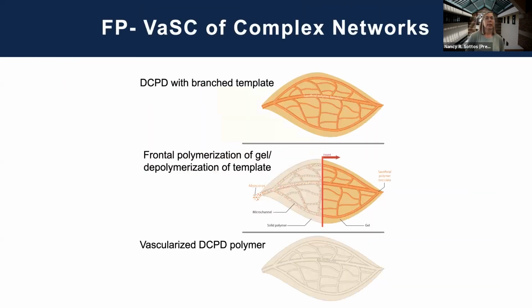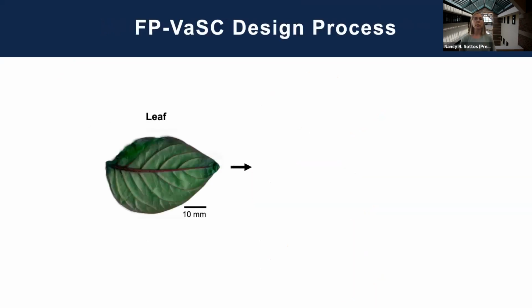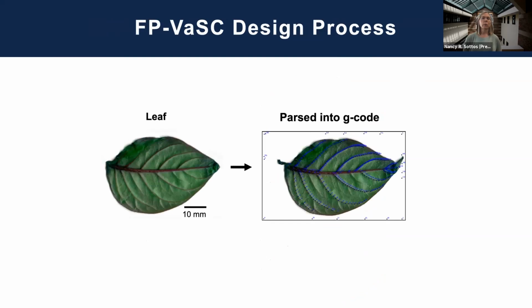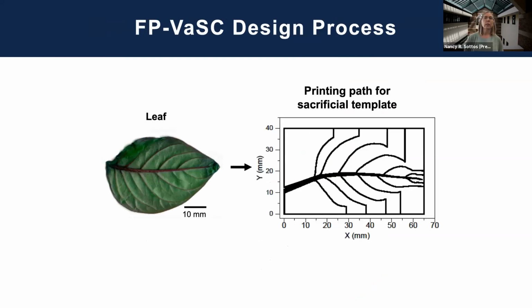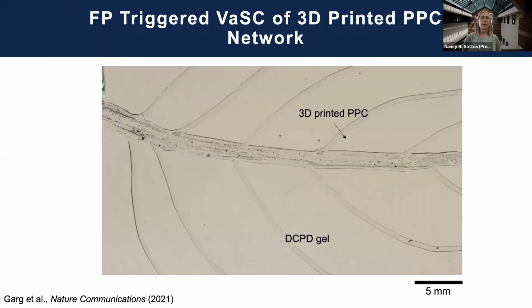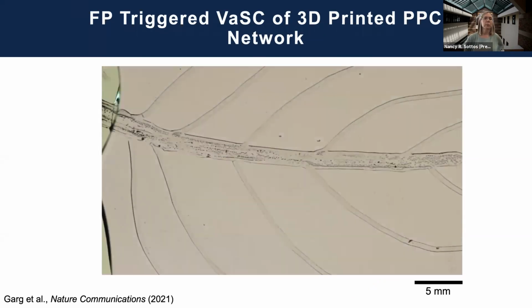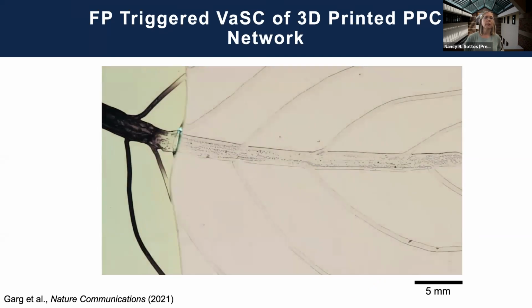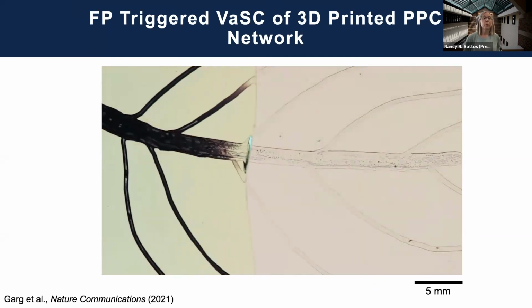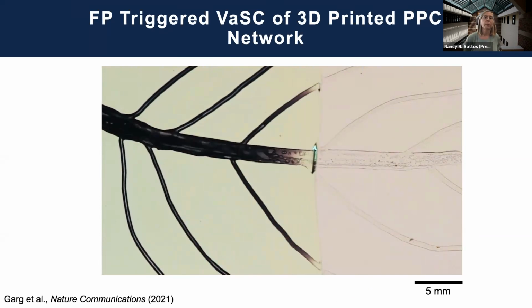We are able to extend this into more complex networks where we 3D print the sacrificial template, embed it in, and then vascularize it using the frontal polymerization. And so in this design process, we started from, as an example, a leaf. We digitize the leaf and parse it into G-code, create our sacrificial template. And this is what that template looks like embedded in our DCPD monomer. And again, the front is going to go from left to right, and you're going to see this polymerization process of the outside polymer material and the simultaneous depolymerization of the template in this fairly complex architecture.